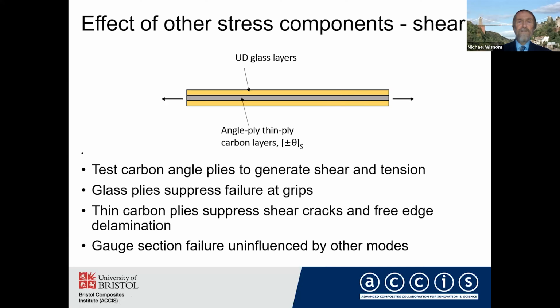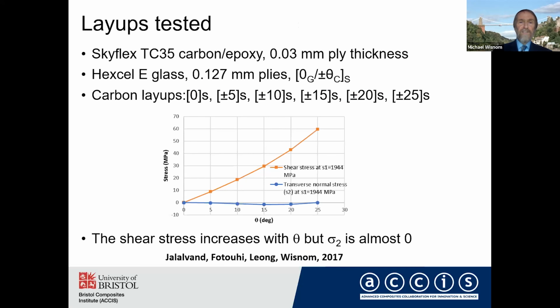And because we're using very thin plies, these are only 0.03 millimeters thick, then we suppress shear cracks and free edge delamination, which might be a problem with conventional angle ply laminates. And we did indeed get gauge section failures uninfluenced by other failure modes. So this high strength carbon epoxy, we tested plus or minus 5, 10, 15, 20, and 25 degrees. And you see that as you increase the angle, the shear stress increases significantly. The transverse tensile stress is pretty low.